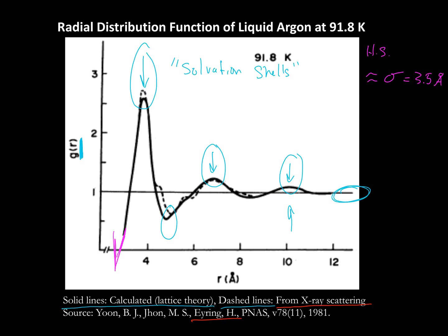So in the Sandler book, this is example 8.1-1. It gives the optimized Lennard-Jones parameters that could be used for a molecular simulation. Right? Lennard-Jones parameters are the most commonly used potential. And for the Lennard-Jones potential, the best fitted values: 3.504 for the sigma, and the epsilon over kB is 117.7.